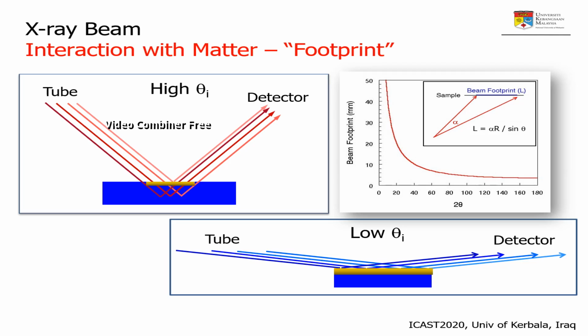As I mentioned earlier, X-ray has high penetration power. Therefore, in X-ray diffraction, incoming X-ray from high incident angle will penetrate deep inside the sample. This is the common scenario in powder X-ray diffraction. Unfortunately, for thin film sample, this situation will result in transmission of X-ray into the thin film support.